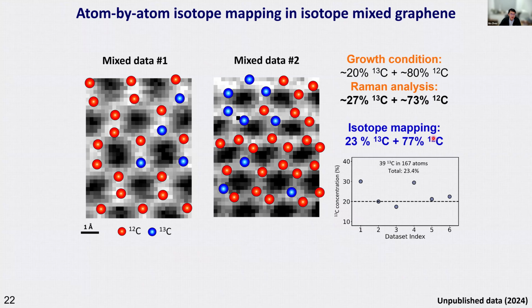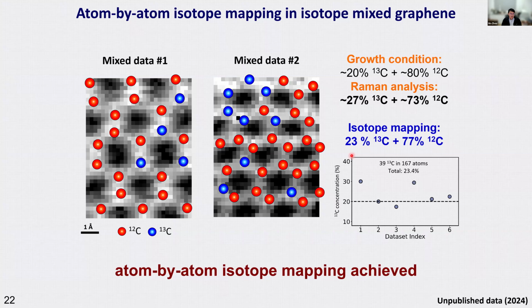And we go one step further to test the accuracy of this whole process. We use an isotope mix sample, just by mixing during the growth 20% carbon-13 methane with 80% carbon-12 methane. And Raman measurement tells us that in this area we should roughly have 27% carbon-13 at the microscale. And at the atomic scale, across different region data sets, we actually get very consistent results.